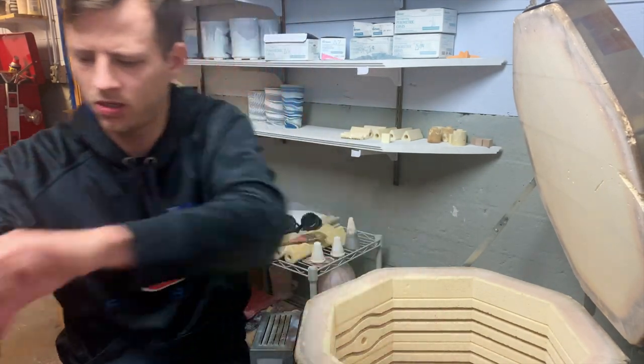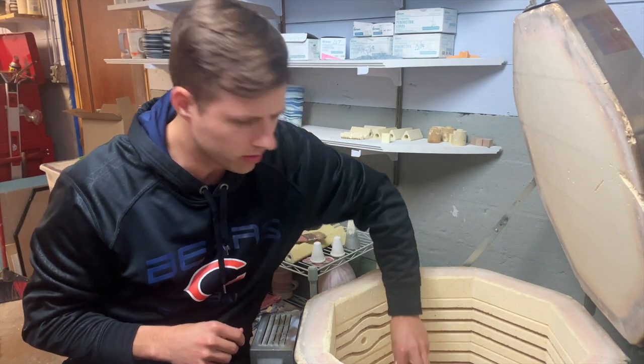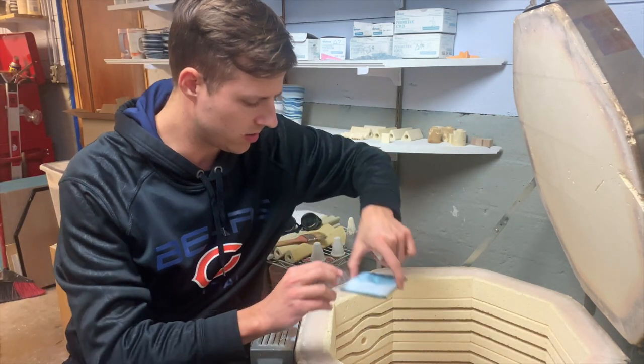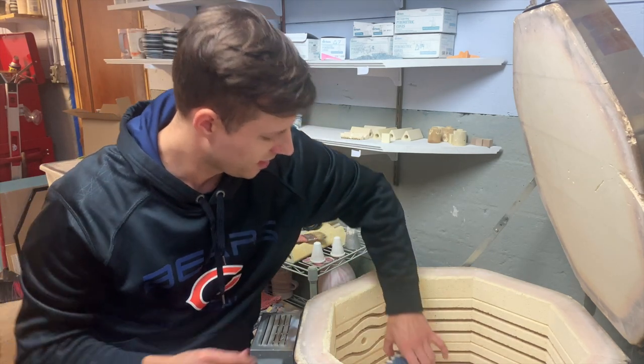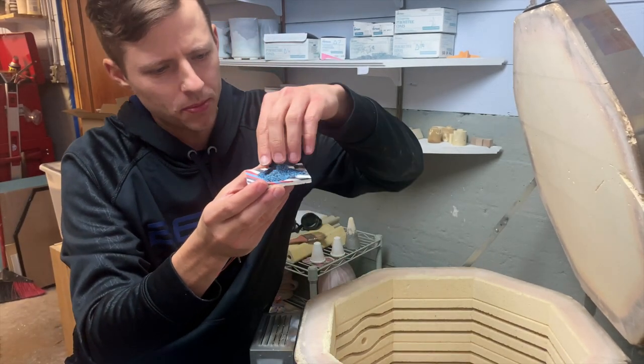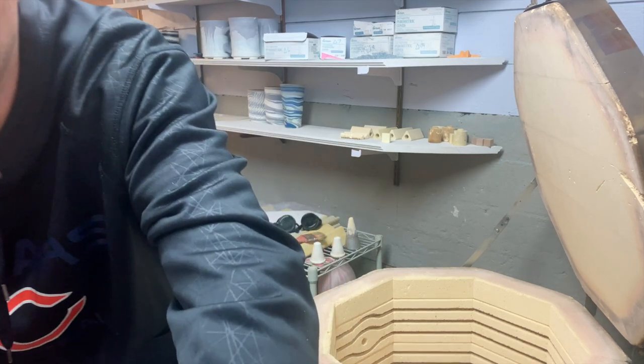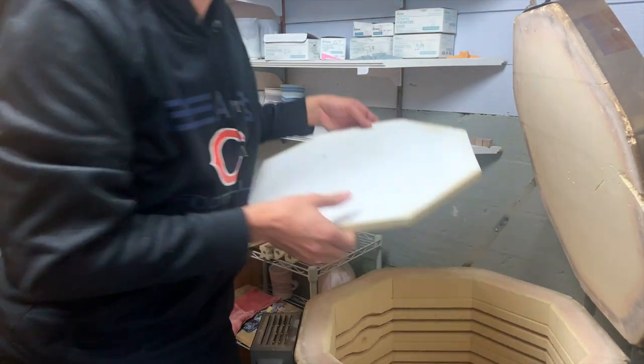A couple of cone packs. Five just started to bend, so it might be a little under-fired — I'll have to see how the other row turned out. Tile test, nothing to report there. I'm also experimenting with firing small shaved chips that I can maybe — I'm not really sure. So we're always doing crazy stuff here in the studio, besides typical glazes and things.